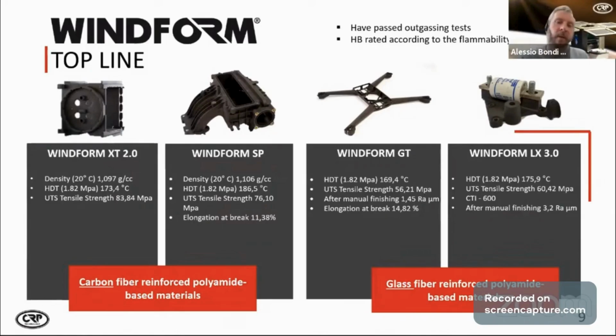Then we have its bigger brother, Windform SP, which is a little bit more heavy. Density is 1.106, but you see HDT is higher, it's 186. UTS is a bit lower, 76 megapascal, but there's a very good elongation at break at 11.38%. Then we have Windform GT that's used for example for drones application.